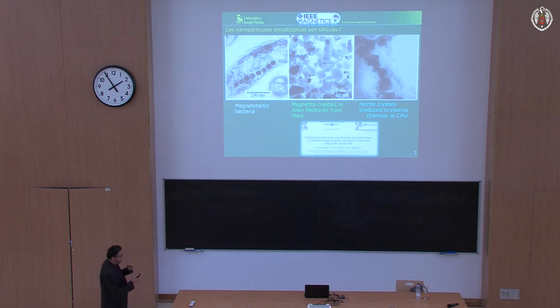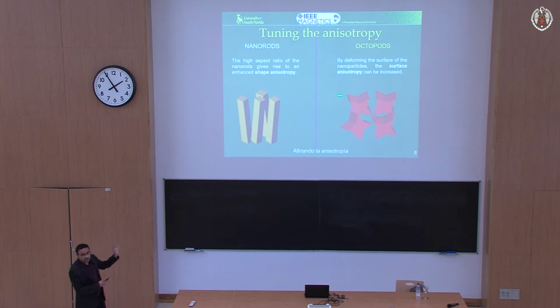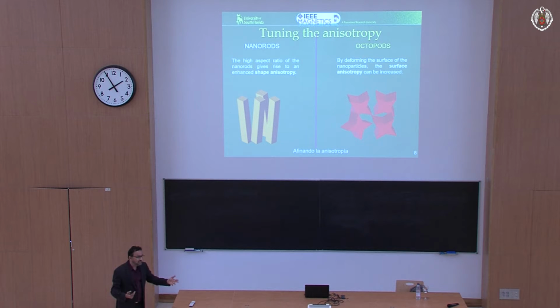All right, so just to give you an idea, when I say tuning the anisotropy, I mean changing the shape. We can call this shape anisotropy, or changing the surface in some interesting patterns. We can do this with solution chemistry. I'll show you nanoparticles later on. We actually have a very good way of controlling the particle shapes and sizes, anywhere between the 5 to 50 nanometer range using chemical methods. In fact, we can pretty much produce any kind of Archimedean shapes now in nano size.